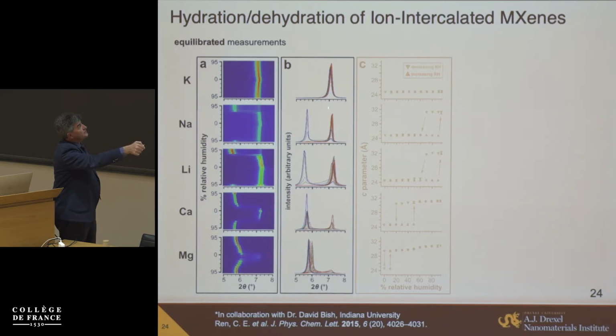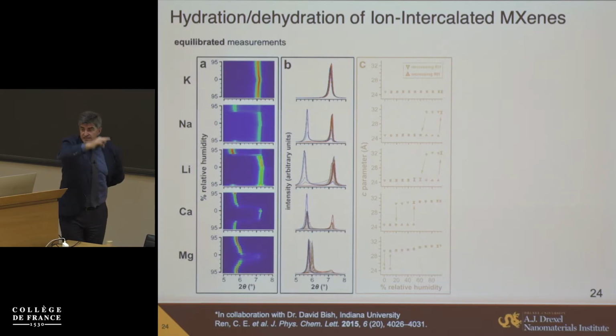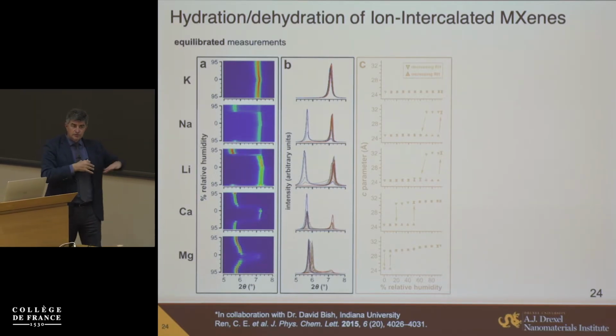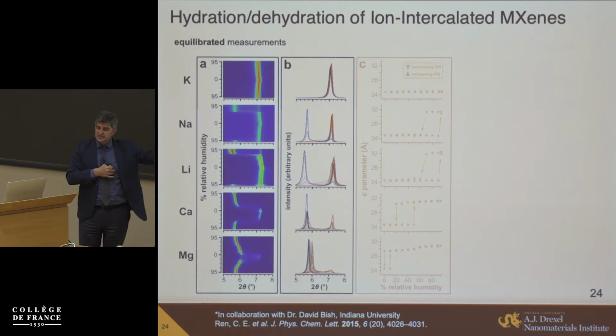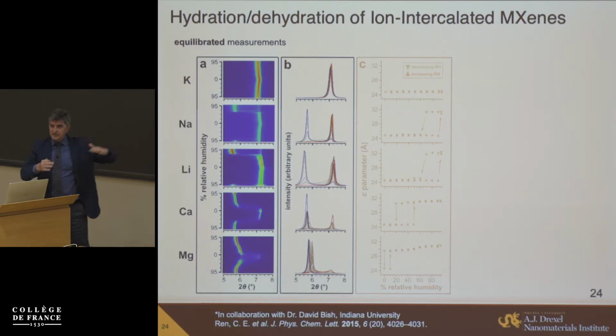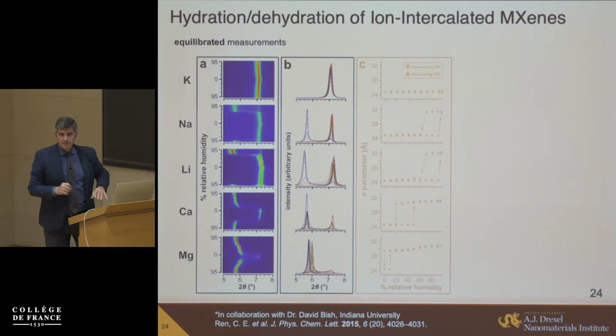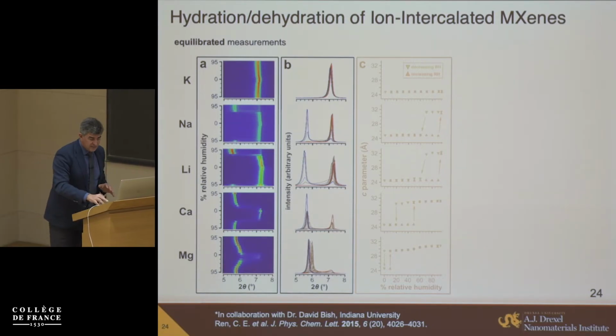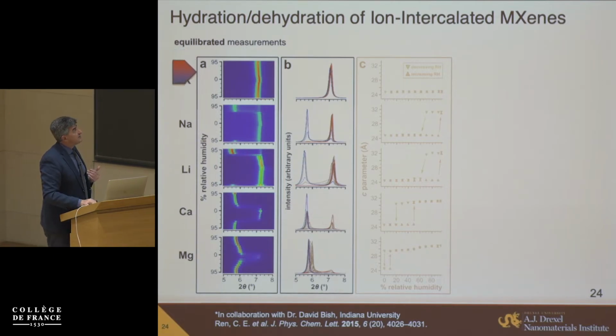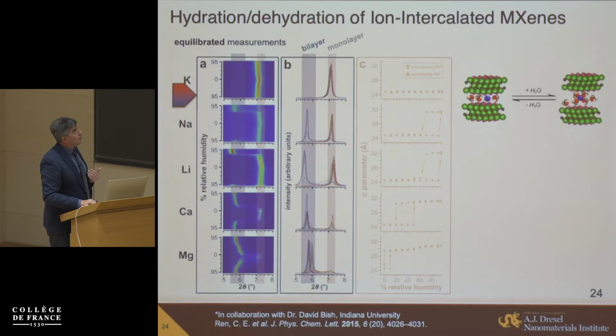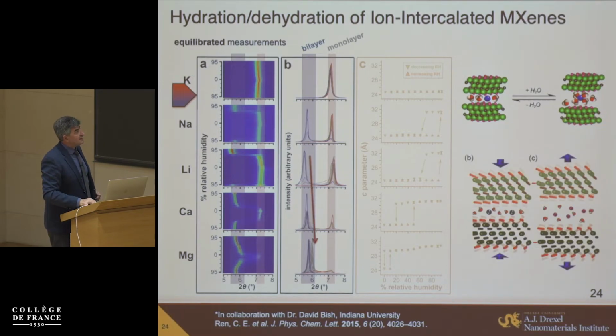And you remember, in case of potassium, there was almost no change in the lattice parameters. And also, when it goes in, it doesn't bring extra water. So it means that you primarily have potassium with an equilibrium number of thermodynamically preferred water molecules sitting there. But again, you have to deal with a different number of molecules as you charge it here. And in situ X-ray diffraction done here shows very nicely how this change happens if you change humidity, and an ion can get more molecules solvating it in confinement.